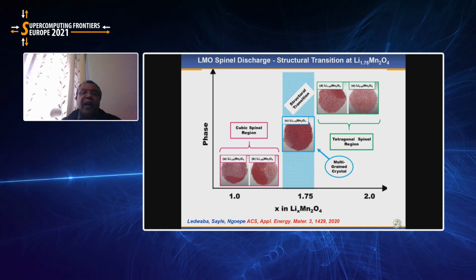Now, the interesting part comes when you try to charge and discharge this material. It moves from what we call a cubic spinel phase to a tetragonal spinel phase. But between these two phases, you have a multi-grained phase at the concentration of 1.75. This is a disruptive phase, which does not make it easy for you to charge from the cubic to the tetragonal region.